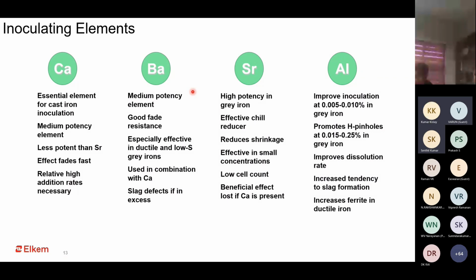Strontium is another superstar of an inoculant, basically. It's one of the best inoculants for grey cast iron. A very highly potent inoculant, it has a very good ability to control carbides, thereby making it the first preferred inoculant, especially for thin section castings. It also reduces the tendency for shrinkage, especially at the thick and thin intersections. You as a user might not have to add too much of a strontium inoculant. So that's one of the benefits.